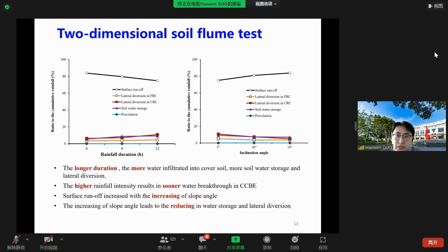And the intensity will also result in a sooner water breakthrough of the top capillary barrier. From the observation for the different inclination angles, we can find that surface runoff increased with the increasing of the angle, and the increasing of the angle will also lead to the reduction in the water storage as well as in the lateral diversion.